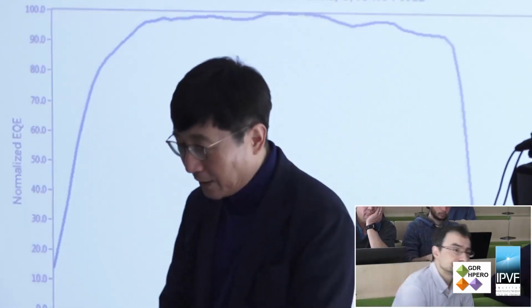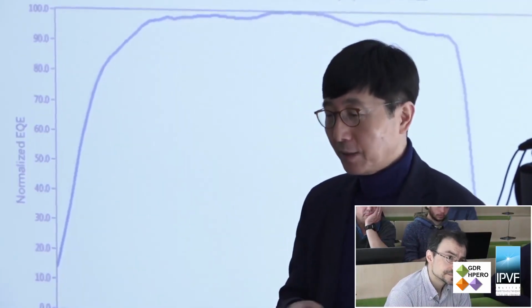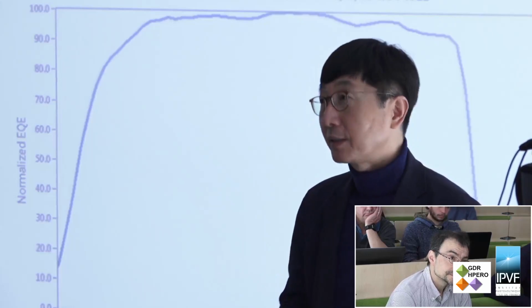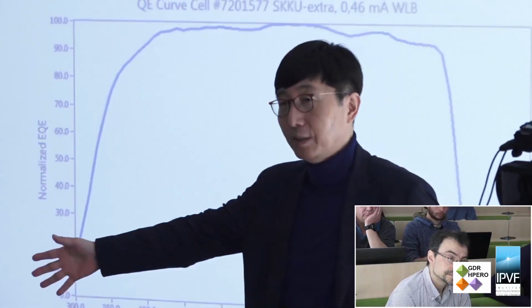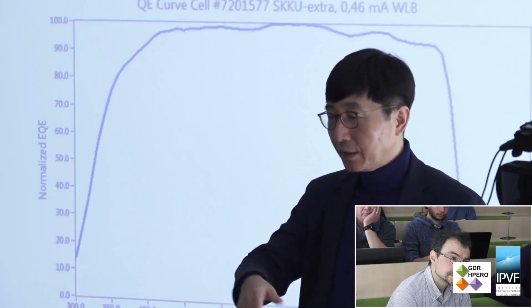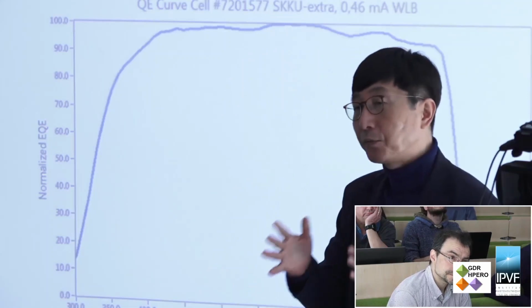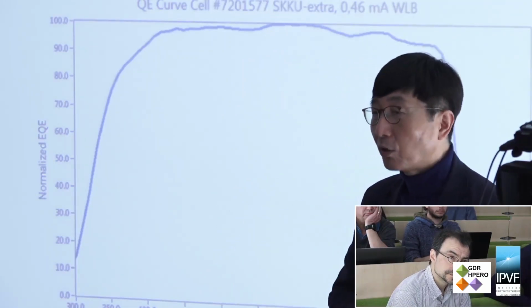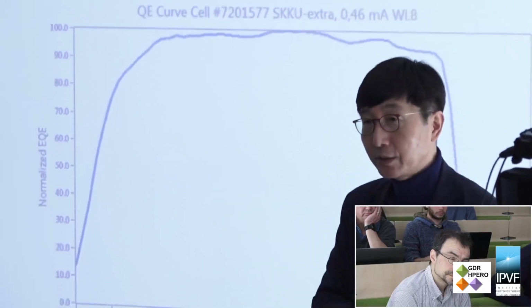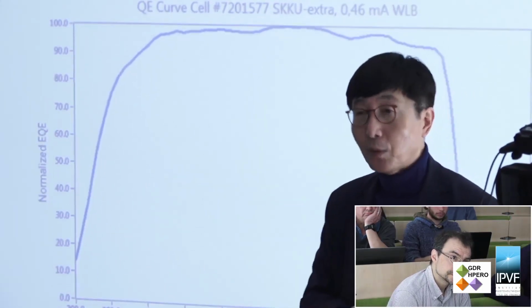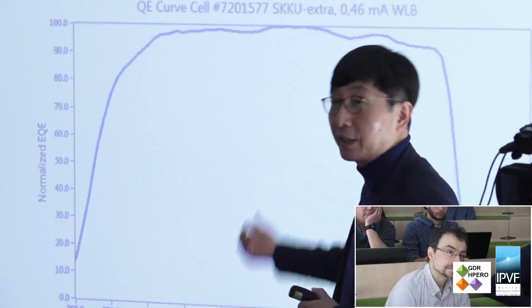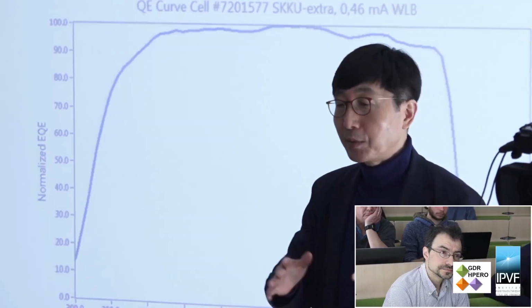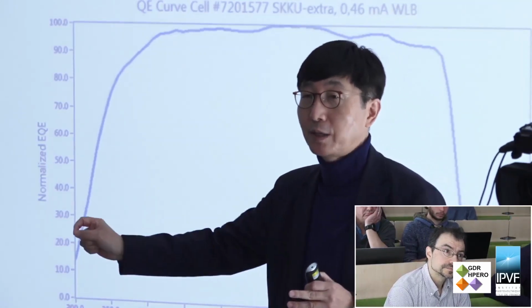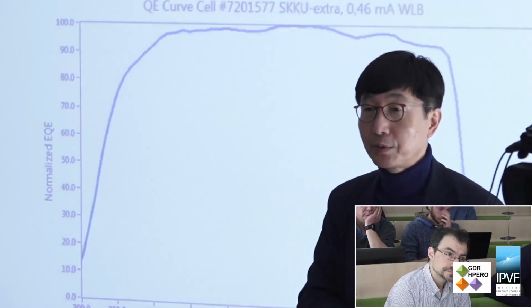Yes. Actually, for that measurement we made a not-real device system, and in that case we did not measure very long term. So in the device configuration for the in-situ PL measurement, we did not measure the long-term stability under device conditions. But for the full cell, we compared the long-term stability under the standard condition with and without potassium ion. Actually, we published it. I did not include this data here in the slides. But we confirmed pretty good long-term stability of the potassium-doped sample, the device.